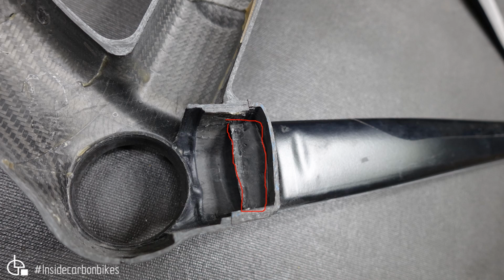But I wanted to show you that rib, because to make that rib with a prepreg manufacturing system is much more complex. But it's actually quite simple to do with resin transfer molding, because all you need to do is have the channel in the mandrel. You place the fiber in that, and when you inject it, the resin fills the remainder of that cavity and wets it all out, and you're getting the pressure effectively from the injection pressure. So it's much easier to do these sorts of ribs with a resin transfer molding process. So you'll see there's ribs. I'll show you some ribs in other areas of the frame as well.